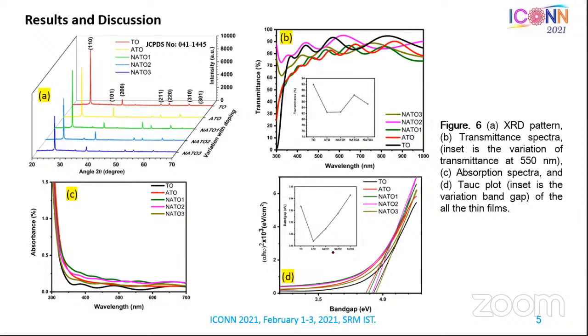This is the band gap we have calculated from the Tauc plot. For pure tin oxide, it is around 3.8. For niobium antimony doping, it decreased to 3.7. Then again it increased with niobium co-doping linearly.